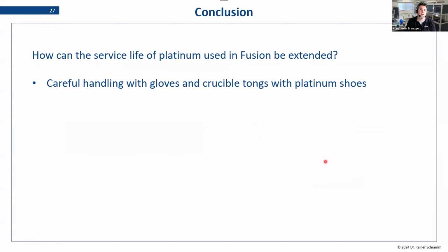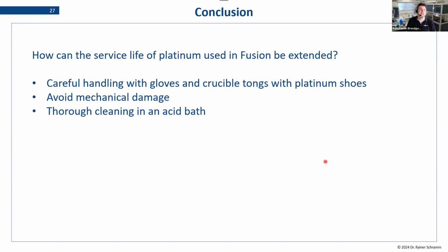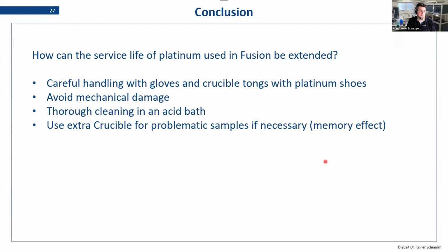So how can you extend the life of your platinum? You definitely want to be careful with your handling. Gloves and holders are a good idea. You want to avoid any mechanical cleaning and any mechanical damage. So don't rub the sample, especially not the dishes. Don't rub them with your lab coat. Not a good idea. Cleaning in an acid bath is a good idea. You can do a cleaning fusion for special samples. Having extra crucibles for problematic samples, the ones with the memory effect, is a good idea.